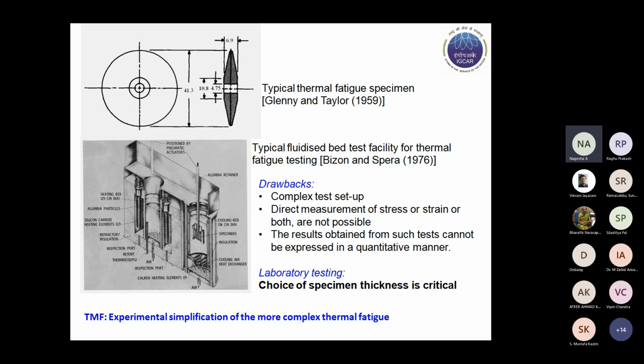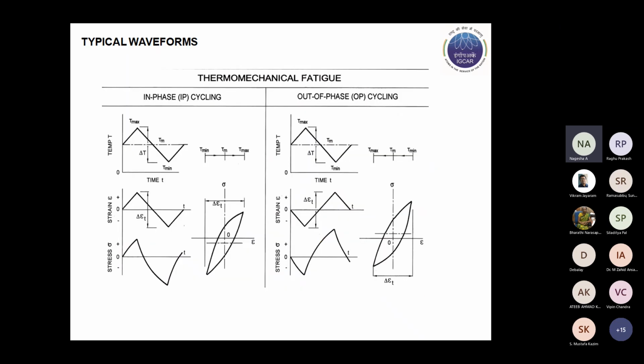However, for a fast enough variation of temperature, you need the thickness to be less also. So from one viewpoint, thickness should be more, so that sufficient temperature gradient is established. But on the other hand, thickness should be less, so that we can do tests at high enough cycling rates. So this becomes a problem. So the experimental simplification of the more complex fatigue is through TMF.